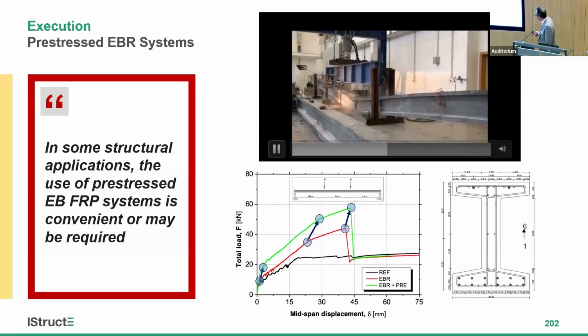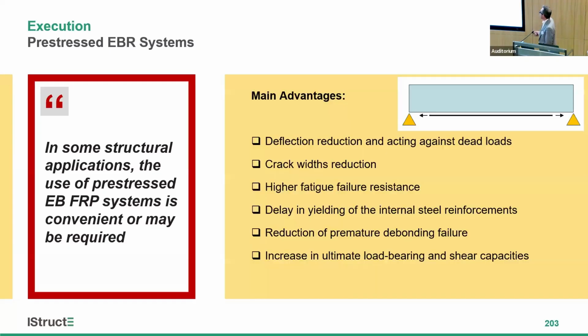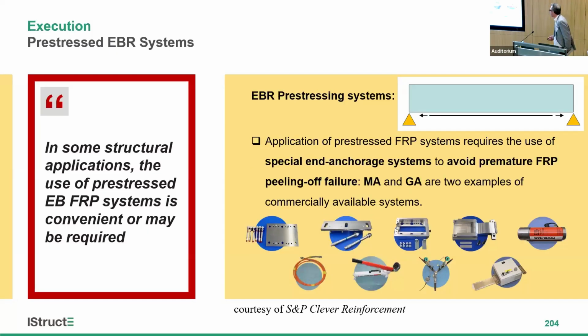So this is the beam without any reinforcement. This is the beam with the passive solution. And here is the beam with the prestressed laminates. So at the end, these are the main advantages when we use prestressing systems: deflection reduction and acting against dead loads, crack width reduction, higher fatigue failure resistance, delay in the yielding of tensile reinforcement, reduced premature debonding failure, and increased ultimate load bearing capacity and shear.